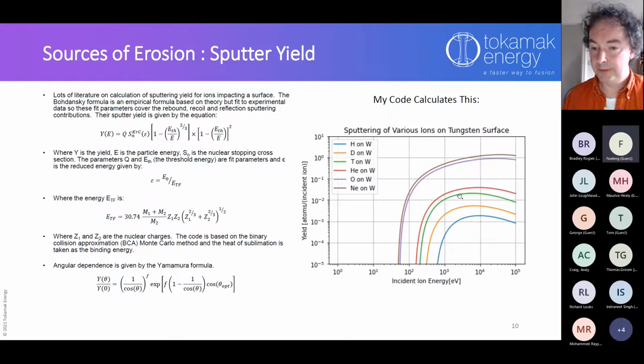And the other exciting feature about this is that it drops right off at low ion energy, which is very useful for us, because it means if we have mechanisms of dropping this ion energy down to maybe 100 eV, we might be able to avoid erosion or minimize it so much, so long as we've just got deuterium, tritium, and helium in there, that erosion doesn't become a problem for us, and our diverter and other plasma-facing surfaces will last for years. So that's the holy grail.